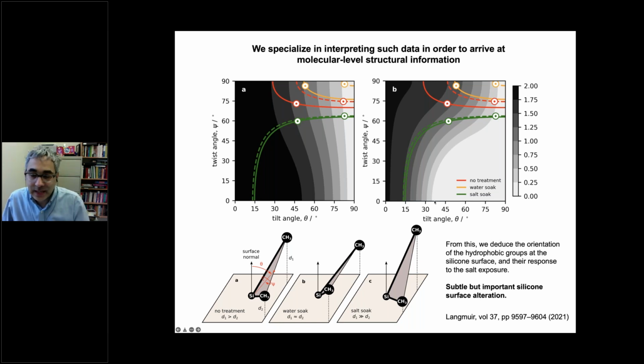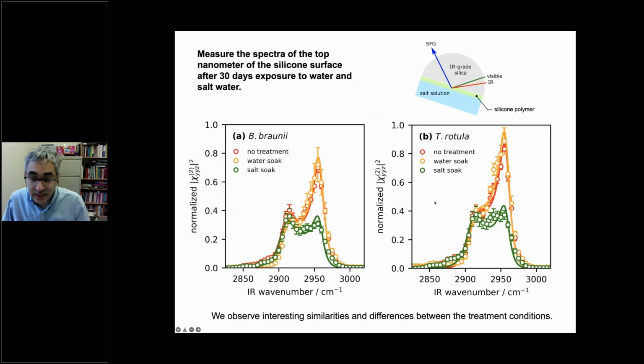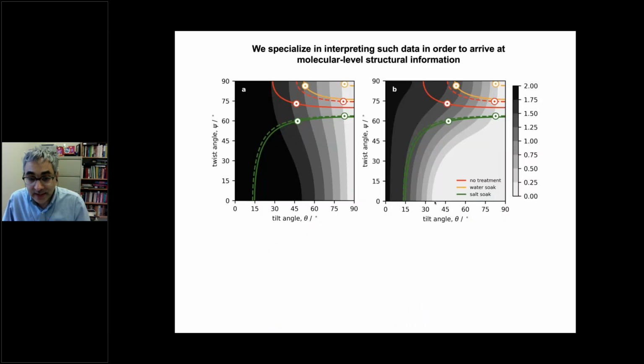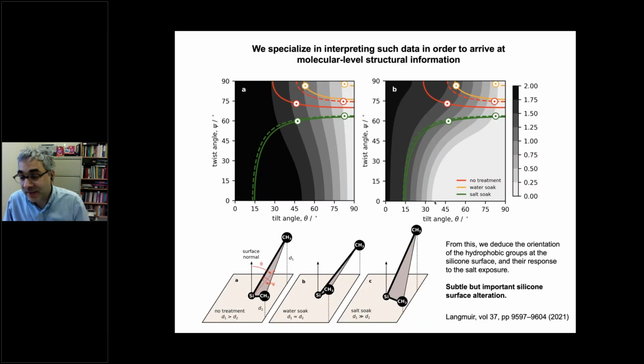And what this analysis has shown, if I go back one slide here, is that these spectra indicate that the plane of the methyl group is tilting with respect to water exposure and salt water exposure. So this is a very small change. It's not as if this methyl group is suddenly burying itself into the bulk silicone phase and flipping upside down. It's just subtly changing in tilt and twist angle. So who cares about this? The algae care about this.